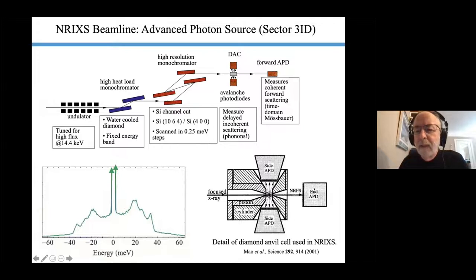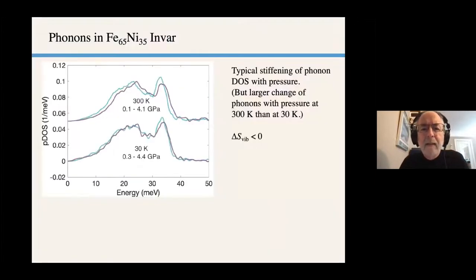We can also nearly simultaneously do nuclear forward scattering, where we look at the time signature of the beats between hyperfine levels. These are, as I mentioned, 10 or 100 nano eV, but they have a time structure when they interfere with each other. I'll show you that in a minute. We can look at the magnetism. Here's data we got within the last year for our Invar sample at room temperature and at 30 Kelvin.